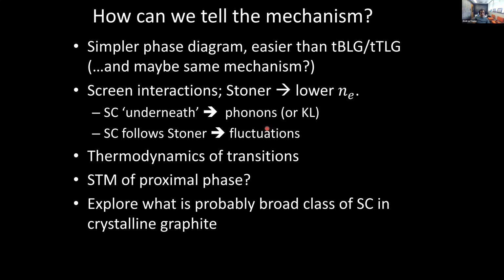So if it's phonons or some generic pairing mechanism, it should just get stronger. But of course, if the superconductivity just follows these Stoner transitions and really depends on the distance from the Stoner transition, then probably that would point towards magnetic fluctuations. In unrelated work, we've also been developing ways to probe the thermodynamics of all of these things. So you can try to look and see what the magnetic susceptibility is, for example, of these superconductors in van der Waals heterostructures, which is quite a difficult thing to do because the number of electrons and, of course, the sample volume of these things is tiny.